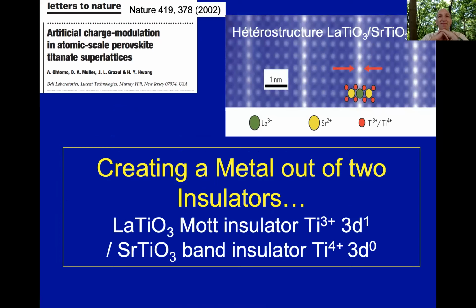This is an example, again, I already showed it, of LTO and STO sandwiches. STO is a band insulator, LTO is a Mott insulator, as I mentioned before. But when you make this sandwich it actually has metallic properties. And the reason why this happens in this case is fairly easy to understand. It's because you can have a charge transfer from the titanium 3+ band of lanthanum TiO3 into the empty d shell of STO, in which the titanium in the bulk is nominally 4+. So you can have part of an electron which jumps from some of the titanium 3+, which get converted then into 4+, into the STO. And that basically amounts to doping LTO and hence to metallic properties.